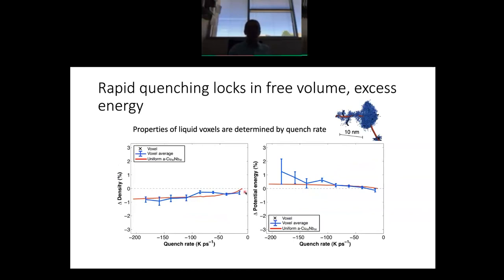What we plot here is the density of the thermal spike core as a function of the quench rate that the thermal spike experienced. First of all, notice that the quench rates here are enormously high, on the order of hundreds of kelvins per picosecond, so 10 to the 14 per second type quench rates. As a result, there's a drop in density in the thermal spike core on the order of 1%. That's basically because of the rise in free volume of the material due to the rapid quenching.